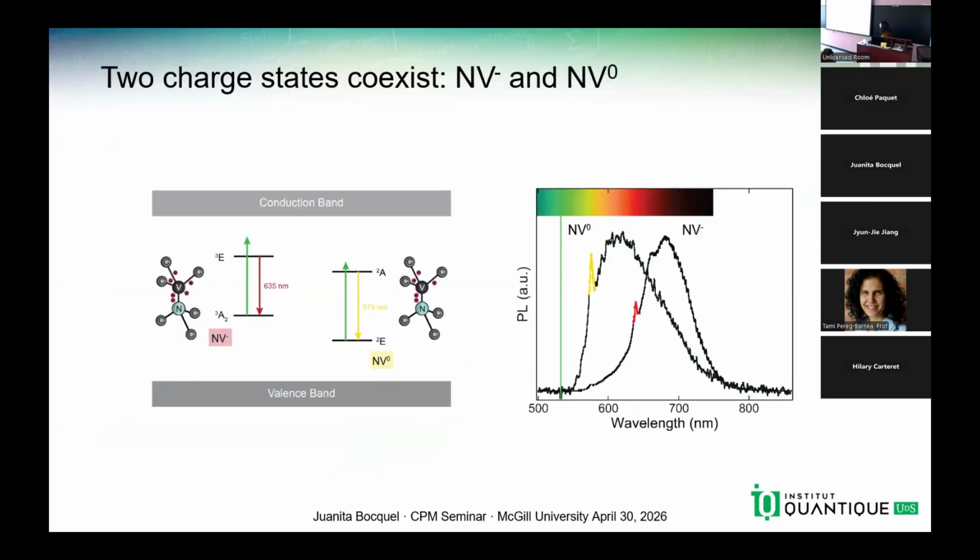Just so that I need to mention something I haven't so far, is that all these I'm mentioning NV centers, but in fact, I'm only talking about the NV center that is in the negatively charged state, NV minus. This is the object I've looked at. But there's a different charge state in which each of these defects spends time. And this is the neutral charge state. So when it loses this electron, and you can already tell that if it loses the electron, this is a bad sign for anything that relies on the spin of this center.